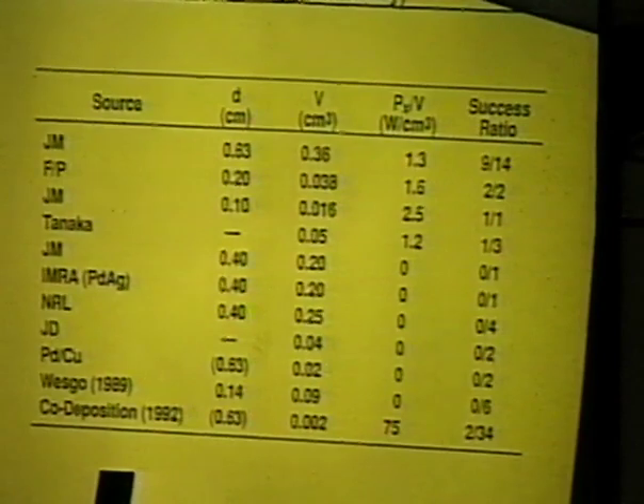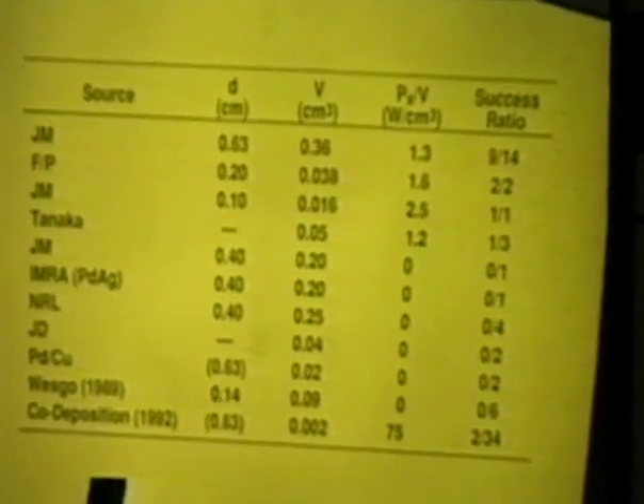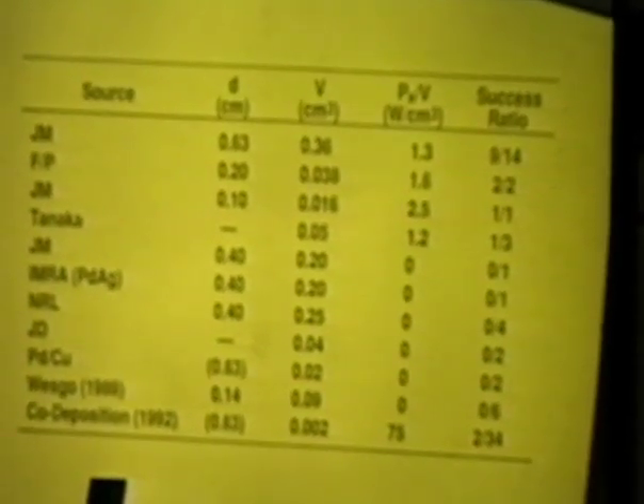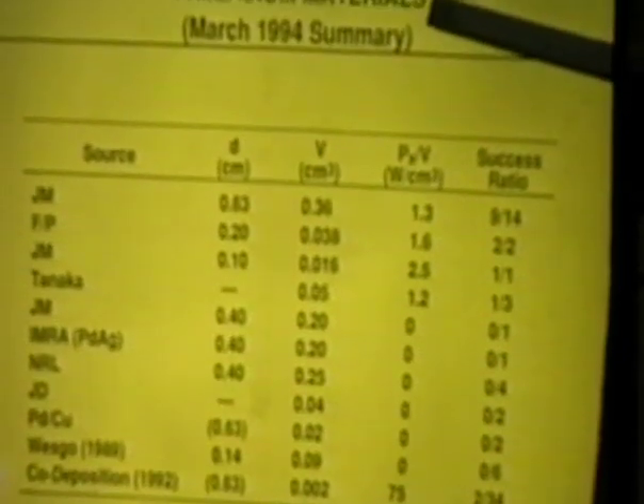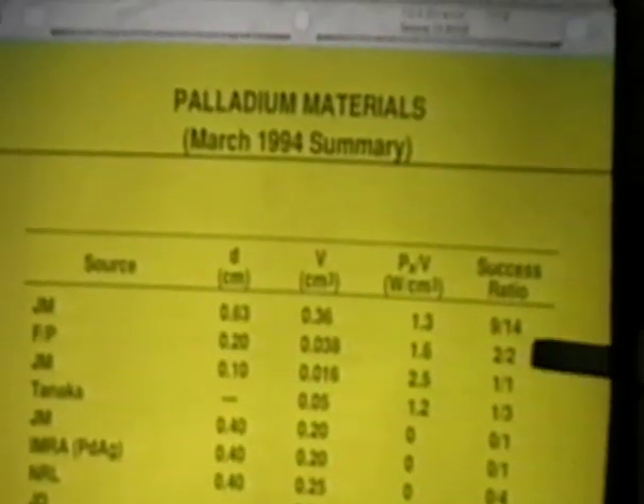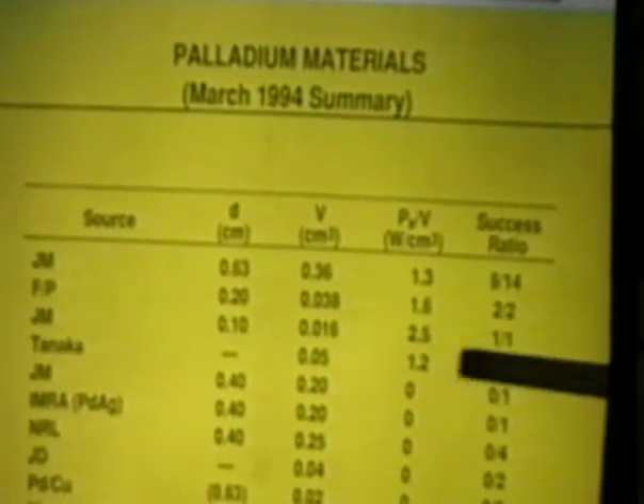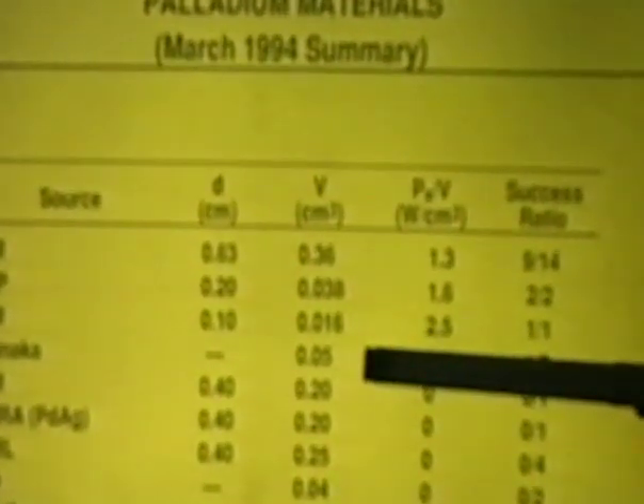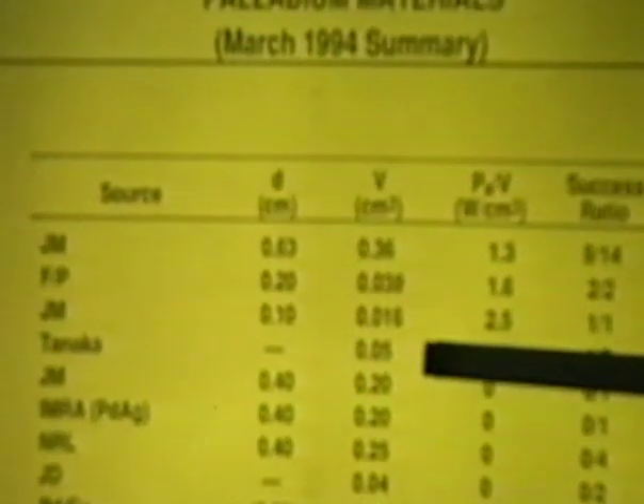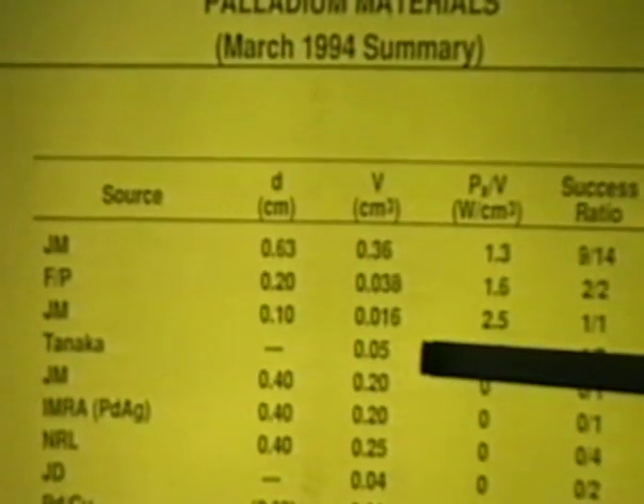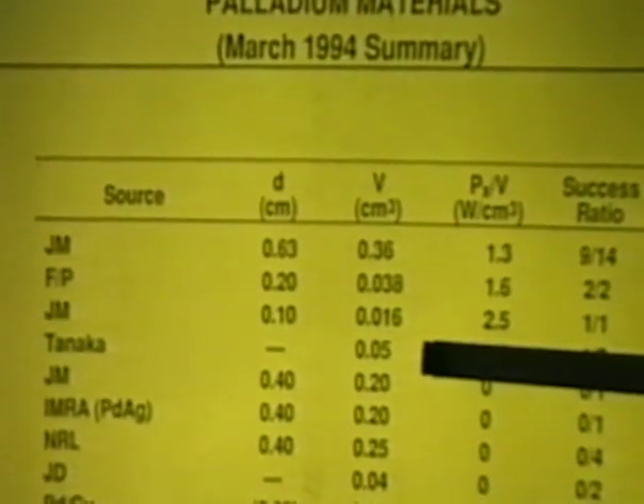Okay, the battery's dead on that other thing, but the main thing of this slide is what other people mentioned this morning, Mike McKubre and others, that the plating material that we use is very important. The Johnson-Matthey, Fleischmann and Pons, and other Johnson-Matthey, the ones above there were all basically Johnson-Matthey materials, and you can see that we had 9 out of 14 experiments gave excess heat in that case. So there are some sources of plating that we get that we have a high success rate.